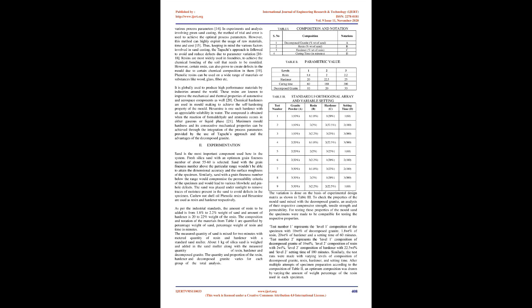Taguchi method has been reported to reduce process variation through a robust design of experiments. This method is widely used for improving design at a very low expense. The Taguchi method achieves robust products that are immune to all noise factors. It involves the construction of a product with limited variation, with close proximity towards the target factor. Analysis through the Taguchi approach provided that the mold preheat temperature contributes as the most important factor for surface finish in sand casting, and the mold hardness increases with the setting time and nature of the resin being used. Taguchi's design with the L9 orthogonal array is known to optimize and analyze the process parameters of a particular problem statement.